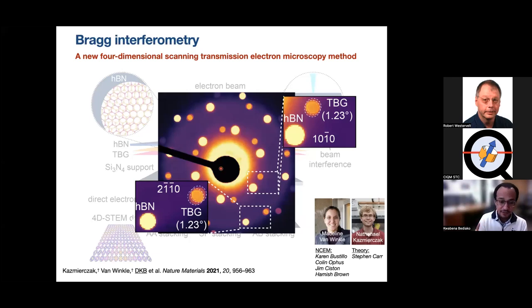First of all, they're very light elements, right, carbon. And also because we're using this converged beam so that we can get the spatial resolution, we have disks now in our diffraction patterns. And so they are overlapping with each other. And so we have low signal to noise generally coupled with overlapping disks that made it impossible for us to accurately enough determine the centroids of each spot or each disk to use traditional strain mapping.